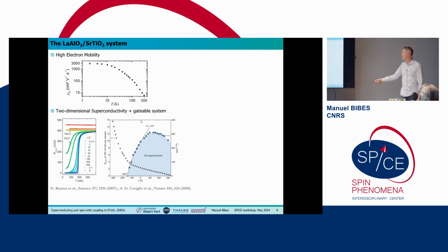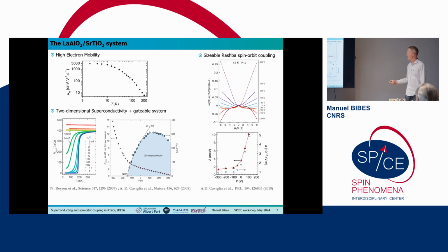And you can here see build this kind of dome-shaped phase diagram, which is reminiscent of that of the cuprates, of course. And together with that, you also have Rashba type spin-orbit coupling. You have some kind of a triangular potential well for the 2DEG, so it's a system with broken inversion symmetry. So you expect to have Rashba spin-orbit coupling. This was first discovered from signatures in the low-temperature magnetotransport. This is a weak anti-localization. And if you do an analysis of this data as a function of the gate, as you can see, you extract a value of the Rashba coefficient, which takes values up to maybe 50 meV angstrom. And as you can see, this is strongly tunable with the gate.